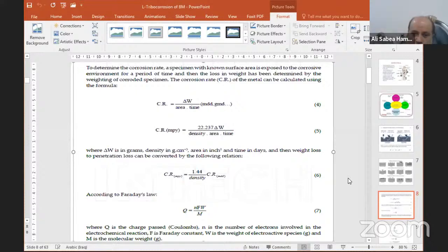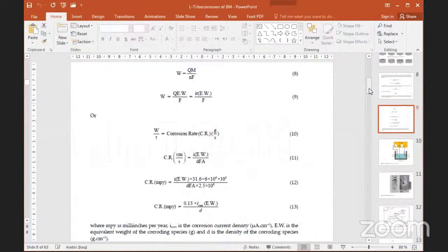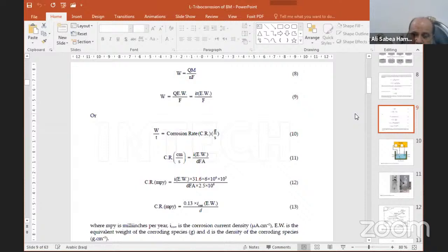The corrosion rate equals 1.44 divided by density times corrosion rate in MDD. Corrosion rate in MPY equals 0.1288 times I-corr times equivalent weight divided by density, where MPY is milli-inch per year and I-corr is the corrosion current density in microampere per square centimeter. The equivalent weight is of the corroding material, and the density of the corroding material is in gram per cubic centimeter.